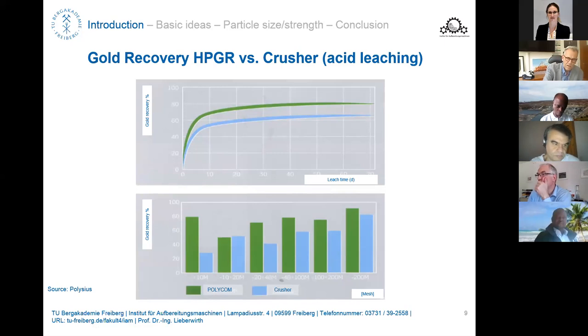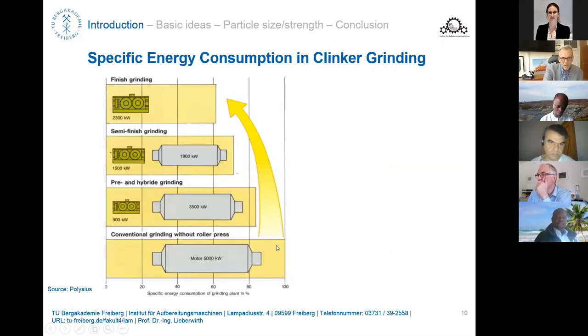So now in some areas these machines are used, but here we are not so much looking at the confined bed comminution as such, which is what we want to see now. Because for leaching systems, usually you are not focusing on the production of too many fines. If the fines content is too high, the permeability of the leach bed would be too low, which would not be good for the process.